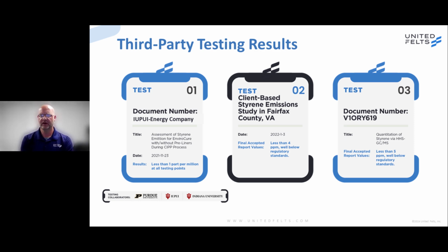We also performed another study with an installation contractor in Fairfax County, Virginia. They were installing 8-inch EnviroCure liners, and they found that less than 4 parts per million of styrene content were found at multiple places throughout the installation site and crew work areas. And we have one water study that we conducted with an installation crew in Florida where they were monitoring the cure water. So we have test results from the actual cure water before heating, during heating, and at cool down. And these tests show that less than 5 parts per million were found within the water throughout different stages of the water cure testing.